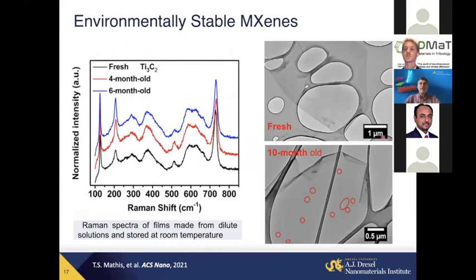Another important factor in application of materials in tribology and many others is stability, environmental stability, chemical stability. And we have recently been really pushing the envelope in increasing stability of these materials, which are thermodynamically less stable than, say, graphite or graphene. And we showed that we can keep stoichiometric, well-prepared titanium carbide MXene, and this is the most common one, the first discovered, most studied, titanium 3C2, in solution for months. Raman spectra show no change after 6 months storage in dilute solution. And even after 10 months of storage, you can see just a couple of pinholes. I circled them here in red because otherwise you won't even notice it here.